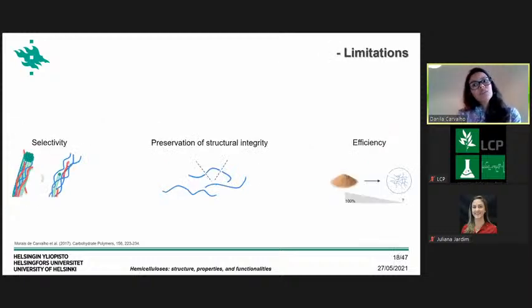But there are also some limitations of the methods, something that we need to take into consideration when analyzing the results that we can get. One of them, or maybe two of them that we need to consider in combination, is the selectivity and the integrity. This is because when we apply some mild method for the extraction of the hemicellulose, it can be so mild that at the end, some other components can be co-extracted together. But if we apply a very harsh condition, what we can have at the end is the degradation of the native structure. So it's important to create a balance of selectivity and integrity, or a balance of the severity of the conditions, in order to have the sample in the condition that we want.